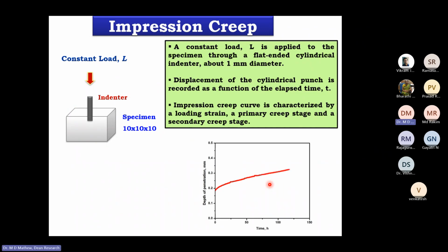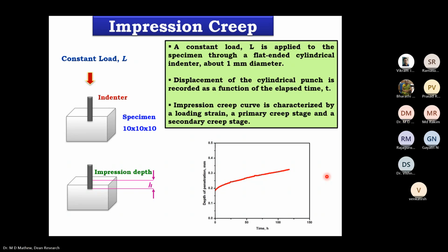So if you plot the depth of penetration data as a function of time, this is what you get. It is similar to a creep curve. You have an initial loading strain, then the transient or primary creep, and then a secondary creep. But no fracture will happen in impression creep because the material is under compression loading. So there is no fracture in this case, but you get a curve which is very similar to the standard creep curve.